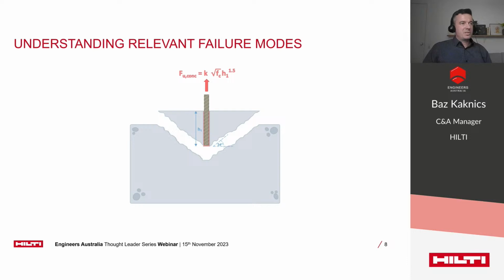After decades of research and tens of thousands of destructive anchor tests, the experts found that the concrete cone actually has a typical shape for the common concrete strength classes, which is characterized by an approximately 34-degree side angle, or in other words, this corresponds to a 1 to 1.5 depth to radius ratio. Based on the existing data, the scientists were able to find a mathematical formula to quantify the concrete cone resistance, which, as you can see, is a relatively simple function of the concrete strength and the embedment depth.